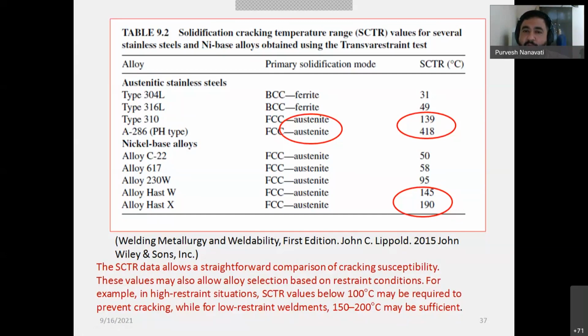when you are repairing your weld, you are performing a weld under a condition where there is no mechanical restraint, or the material has less restraint to mechanical force. Then you can go for 310, but it's not advisable because of the high solidification temperature range. Same goes with the nickel-based alloy, right? I have not marked this point, but the same story applies. But with the lowest solidification temperature range, 31, and with ferrite mode of solidification, more than safe.